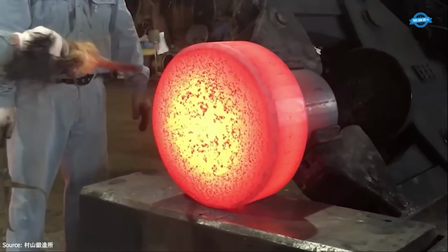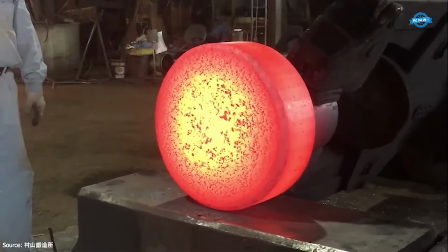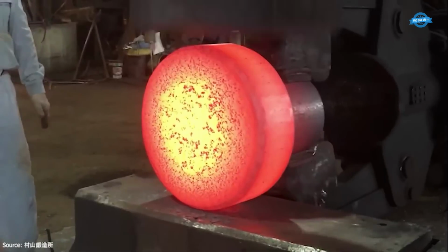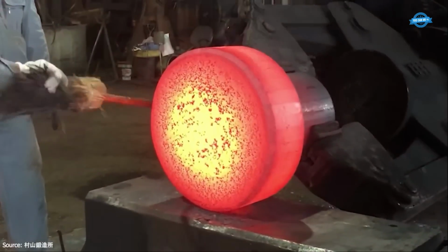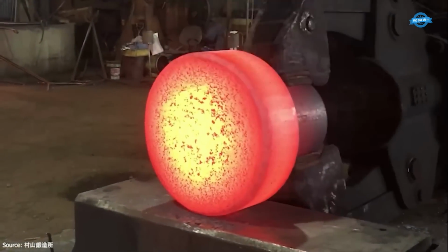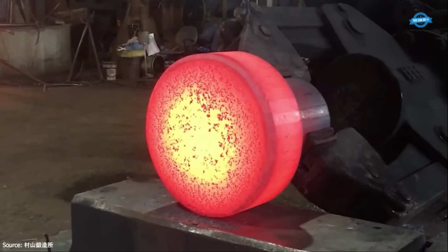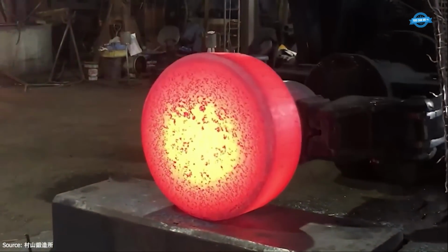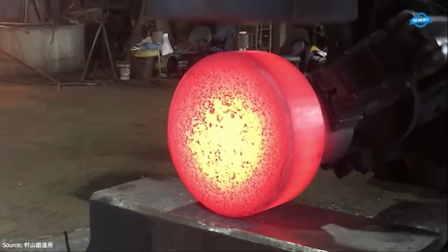Typically, the cooling is performed in insulated boxes or under still air to prevent rapid quenching, which could introduce thermal stresses and potential cracking. Targeted cooling rates for large steel forgings are often around 50 to 100 degrees Celsius per hour, depending on the steel grade and section thickness.